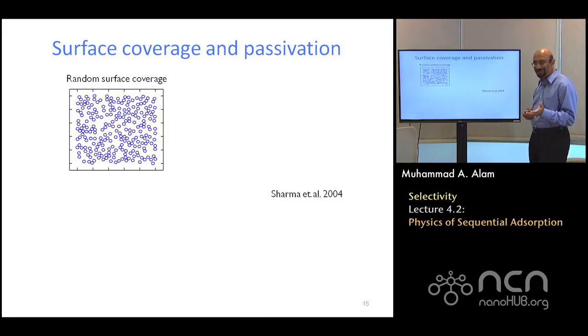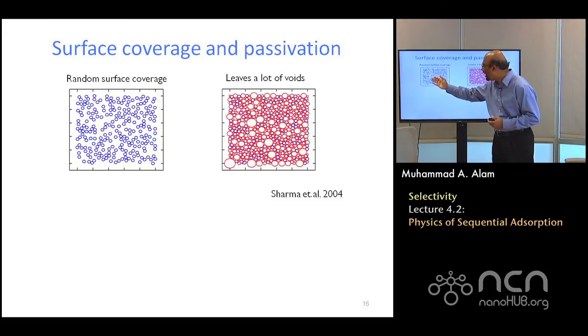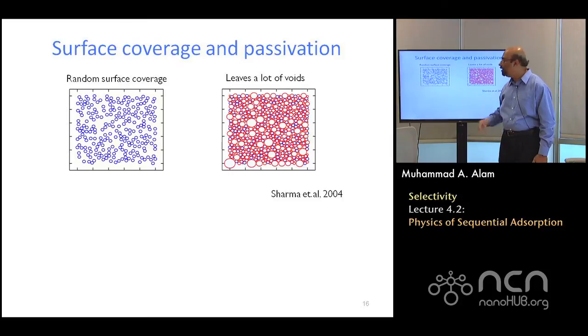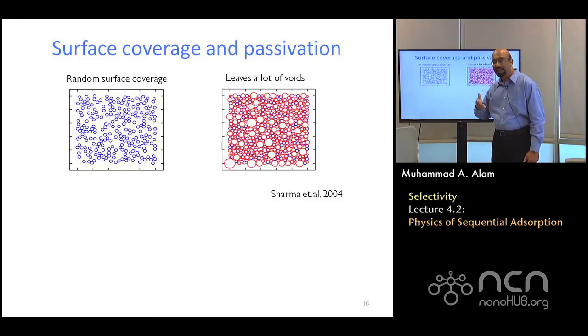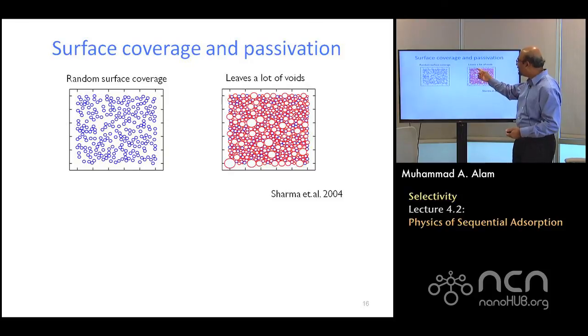Now, are any of these experimentally verified? This is a very strong statement that you will have 55% unoccupied area where molecules can land. It turns out that you can indeed show this. On the left plot, we have the receptor molecules randomly decorating a planar surface, let's say. And you see that this is at a given time. You can see all these empty spaces where parasitic molecules can come in and corrupt your signal. You can try to fit a circle in this empty space to see what fraction of the space is really empty. And these are these big red circles.